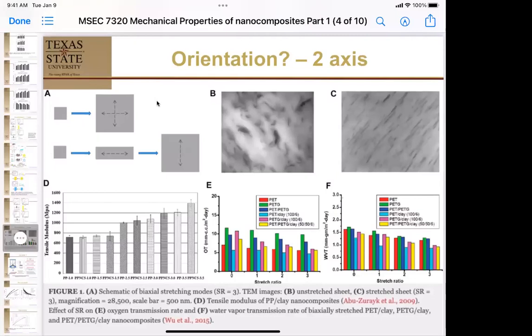I'll double check. You said that if you do both sides at the same time, it will have a different strength than doing it separately. It should have different order. But look at this strength here. The tensile strength in this direction is higher than the tensile strength in that direction. If you did it biaxially, in theory, these plates would be ordered in both directions, and you should have the same tensile strength in both directions. That would be good or not, depending on what you want. In something like biaxially oriented polypropylene, it is so much stronger that it's worth the extra.